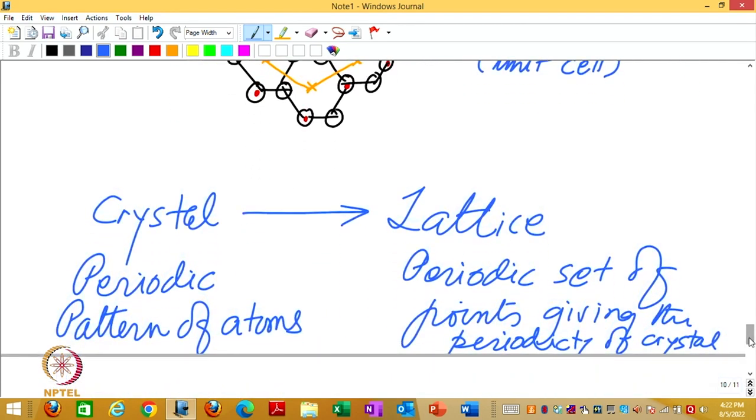From the crystal you can always derive a lattice, so this is unique, but from lattice to crystal is not a unique path. If you want to go back, some more information is required. And what is that information? What is being repeated, because the lattice is giving you only the repeat structure.